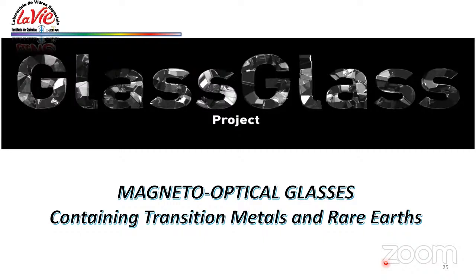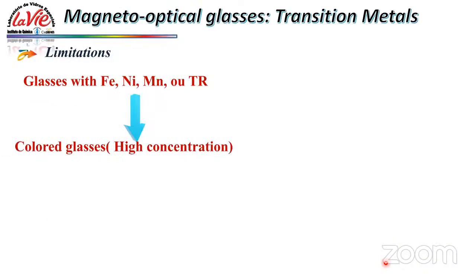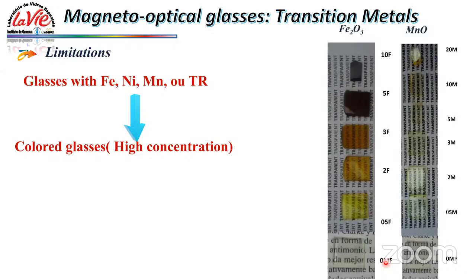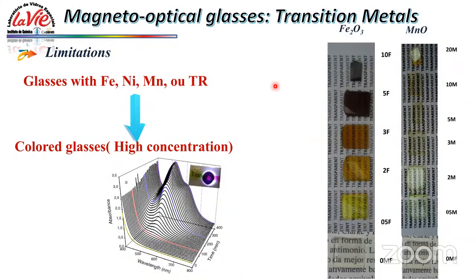The main aim of our research here is magneto-optical glass. We started this study some years ago, working on transition metals, but transition metals have some drawbacks. One of the main drawbacks is that when you try to increase the concentration of the transition metals inside the glass, usually it becomes dark, like here with iron oxide. One of the main possibilities is to work with manganese. If you can stabilize the oxidation state of manganese in just 2+, it presents only one small forbidden absorption band around 410 nanometers, and then we can have glass with an absorption curve like this. This is the yellow one here in the graph.